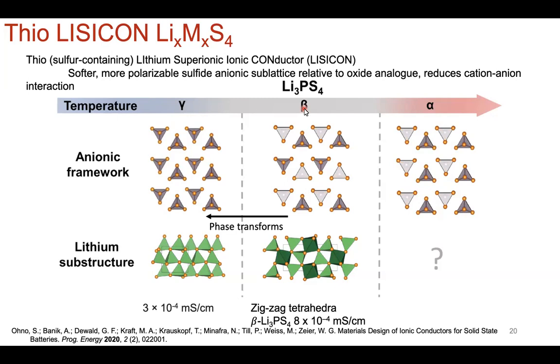And why would you nanostructure it, Patricia? So it's very small. Like the structure is under a lot of stress to get higher energy stabilized that way. Yes, but I believe you're dancing around the term increasing surface energy. Yes, right. So that is the mechanistic way of doing it, but the fundamental theory is that you're increasing the surface energy, but you're stabilizing that high surface energy. And that's what nanostructuring does: it allows you to access phases that you would not normally be able to access in the bulk under ambient conditions. So increase your surface energy and stabilize a higher energy phase that way.